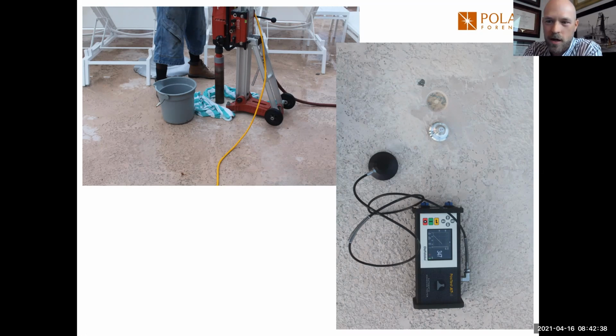And a good concrete petrographer can identify a number of different characteristics of that concrete sample. They can determine what the aggregate type is, the approximate water to cement ratio. If there's any deleterious reactions going on in that concrete sample, they can see it. If a core is taken through a crack, a good concrete petrographer can also identify the mechanism by which that crack is occurring.